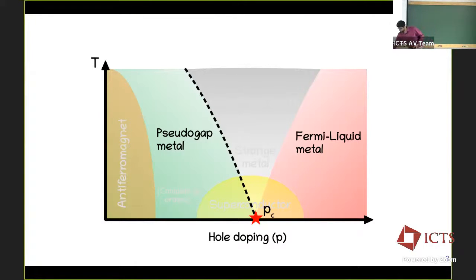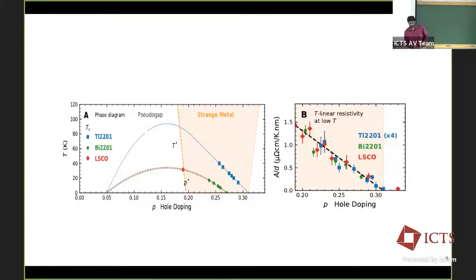This new observation is that, as you can see from the schematic phase diagram, at high doping you expect that everything is basically a Fermi-Liquid metal, and even experimentalists and many of the people in the community did not pay much attention to this overdoped region or high doping region of cuprates, presuming that it's just an ordinary metal. But interestingly, recent experiments have found that even in this overdoped region, for a considerably large doping domain, almost 10%, you still find strange metal type of anomalous transport signature.